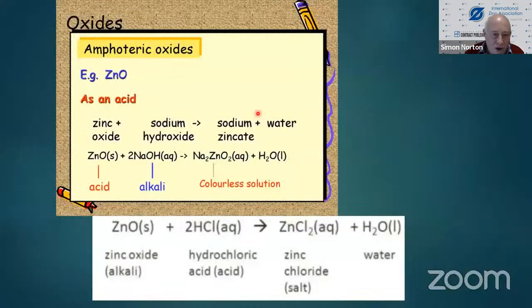Now, as I mentioned earlier on, zinc has a peculiarity which you need to watch out for. If, for instance, you use a galvanized roof that isn't coated, or a hot-dip galvanized steel structure, and you use it in a wastewater treatment works, if that wastewater treatment works liquor or water becomes acid, then you will get a reaction between the acid, the zinc oxide, and a base. Sorry, if you've got a basic solution, which is quite possible because wastewater can vary depending on what's dumped into it by the users.